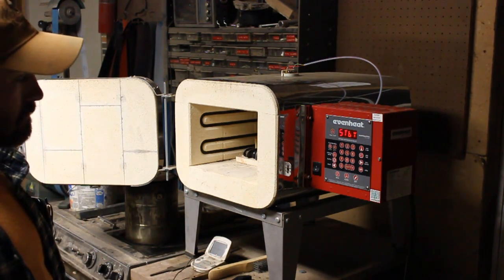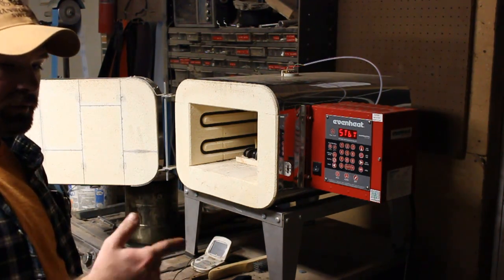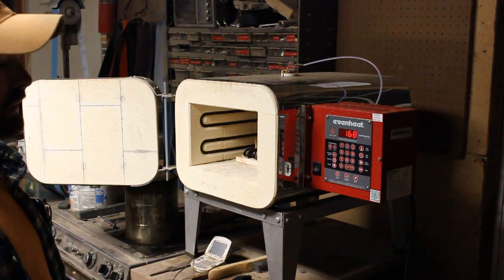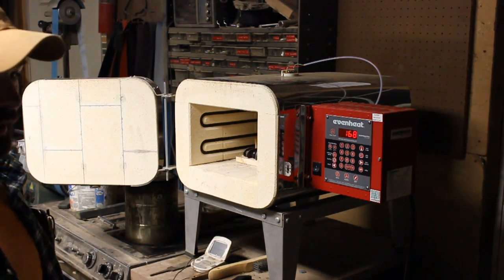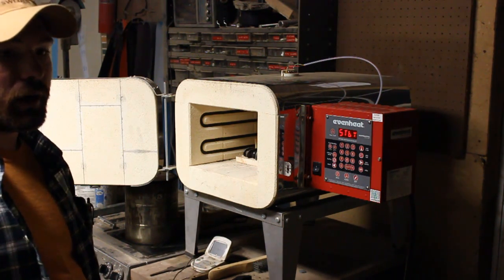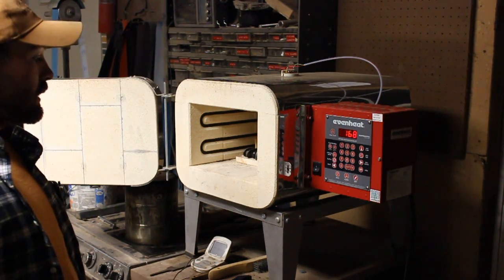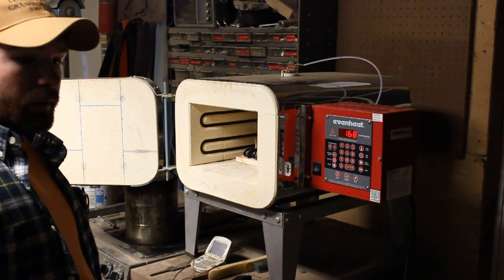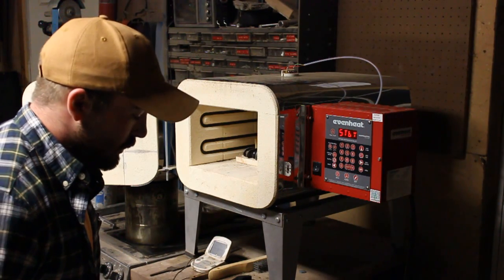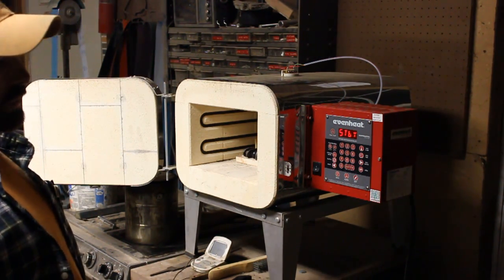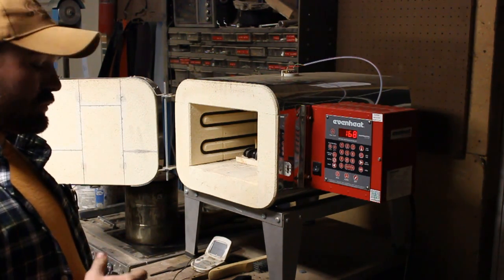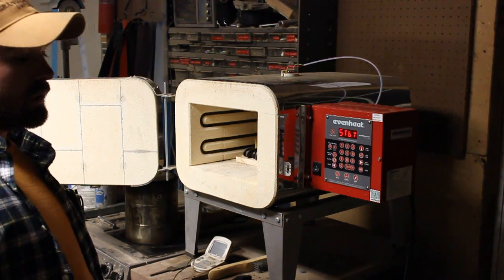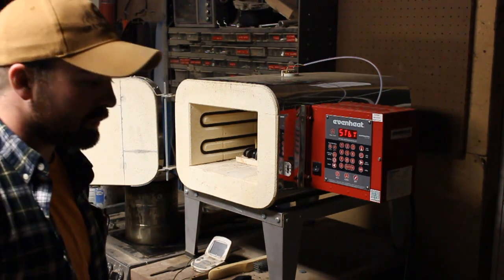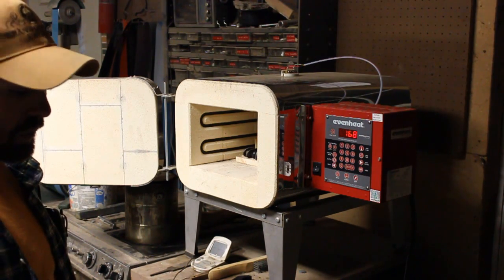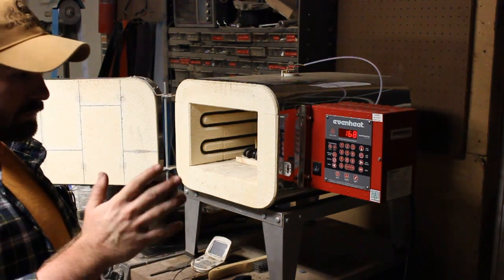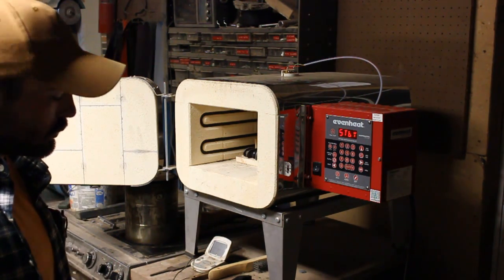Should I try to actually program it to do all 3 tempering cycles in the middle of the night, it actually won't be able to do that, because after the first tempering cycle being held for 2 hours and just the ambient temperature in the shop being what it is, it's still trying to get back down before it can get started on the next ramp. So what I end up having to do is I have 3 different cycles programmed. As you should, drop the temperature 25 degrees for every subsequent cycle that you do when you're doing multiple tempering cycles. Again, depending on the steel, I'm not sure what other steels are. O1 tool steel, 25, 50 degrees, something along those lines, depending on your sources.